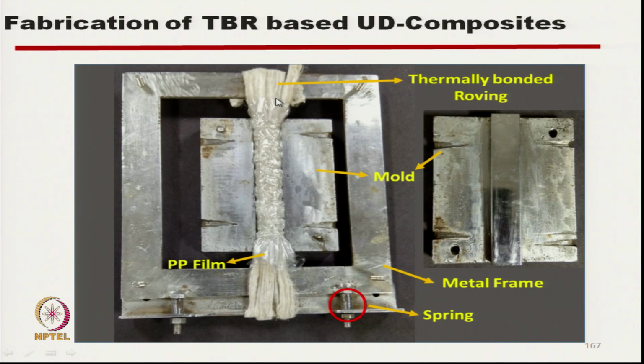This is the photograph of the composite making process, which is for unidirectional composites. These are thermally bonded rovings, parallelly laid, this parallel laid TBR, and these are the PP films. This is one of the PP films. So, layer by layer it has been placed in the mold, and this is the metal frame, and by compression molding the composite was manufactured.